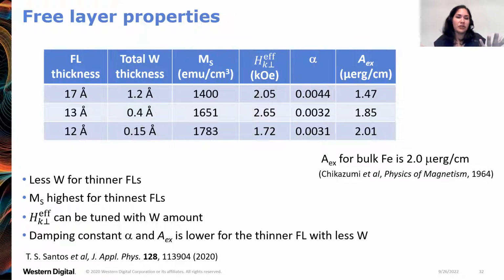Here, what we're finding is that we're starting already very low. We have this effort to have very good magnetic properties. You see that the Ms is very high. We're taking out this heavy metal. This is what's driving the damping parameter lower than what's already low. But I do know that if we try to push and go smaller than this, then we start getting an increase of inhomogeneous broadening and an increase of damping parameter. Yeah, definitely. This is just 1 nanometer almost.